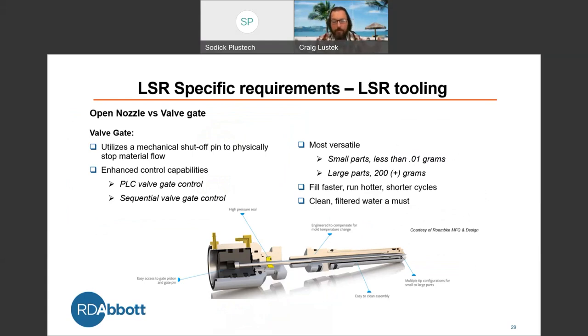Valve gate, most versatile. This utilizes a mechanical shutoff pin to physically stop that material flow. You have enhanced capabilities for control, PLC, and sequential valve gating. As I said, it's the most versatile. Small parts, less than 0.01 grams, up to 200 plus gram parts are possible to run with a valve gated nozzle. You can fill faster, you can run hotter, have shorter cycles. But again, clean filtered water is a must.